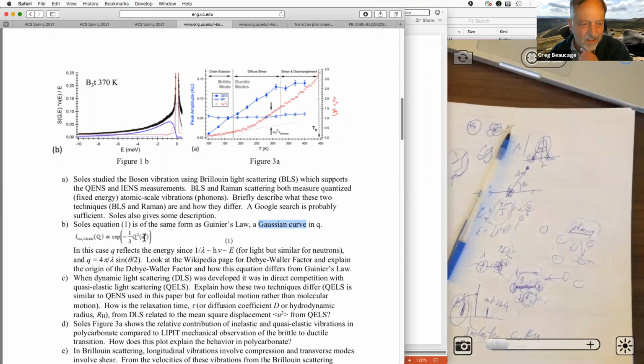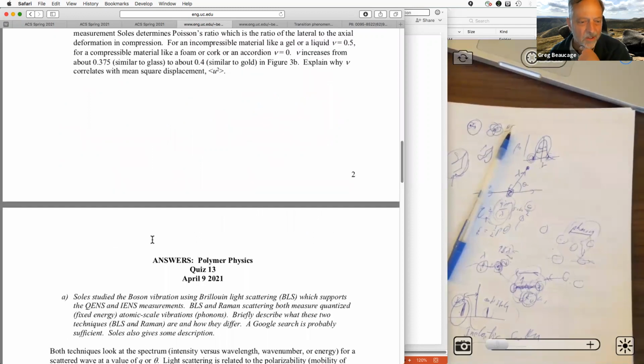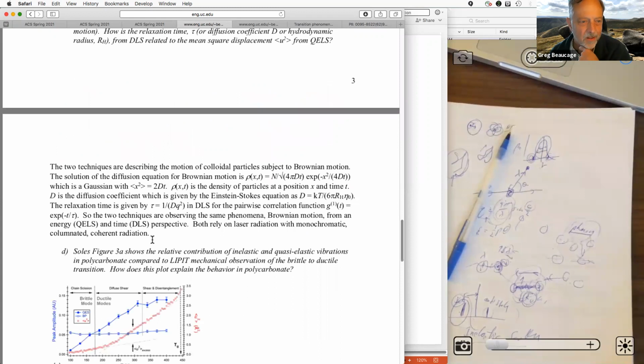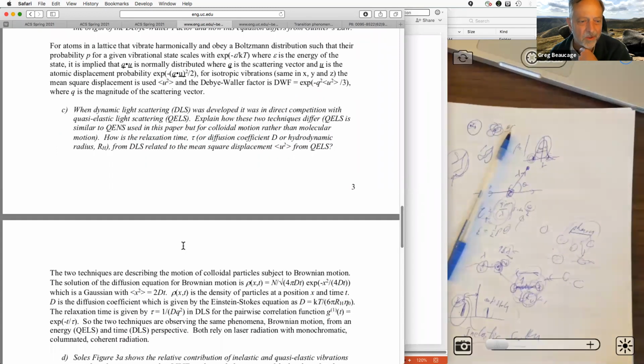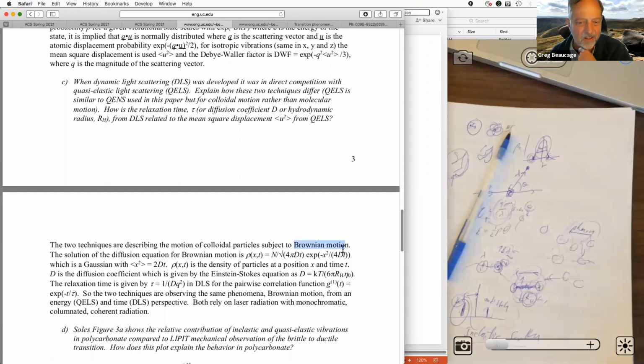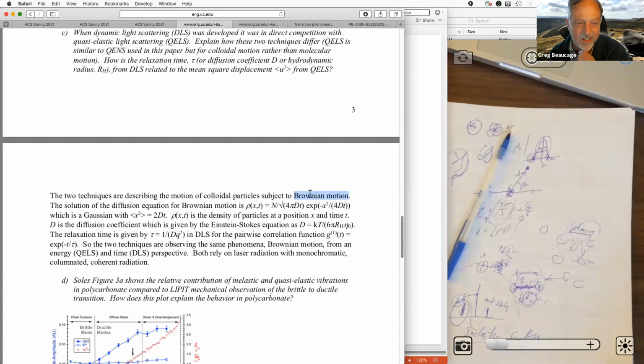Right, so here you're interpreting this as the mean square displacement, okay, of what? Of a Brownian motion, right? So that's what links together the QELS and the dynamic light scattering, is that they're both looking at Brownian motion. So once you realize that they're both looking at Brownian motion, then just like Wikipedia Brownian motion, you find out that the solution to the diffusion equation for Brownian motion is, guess what, a Gaussian, a bell-shaped curve, exponential minus x squared over 2 sigma squared, where sigma squared is the mean displacement, 2Dt, with D the diffusion coefficient.